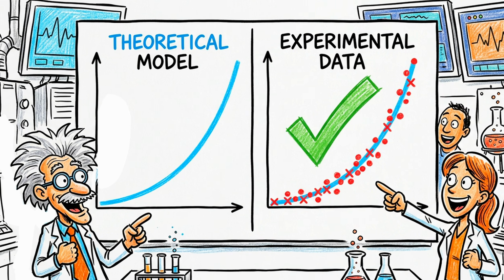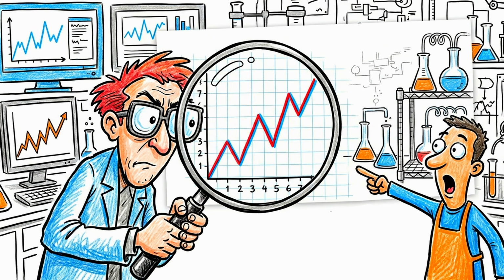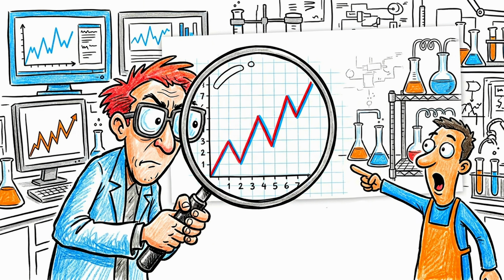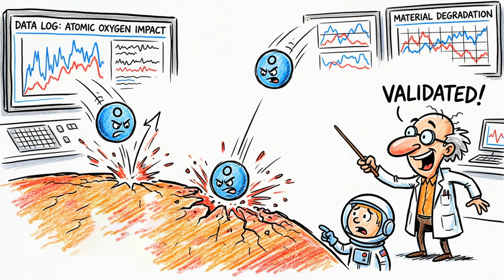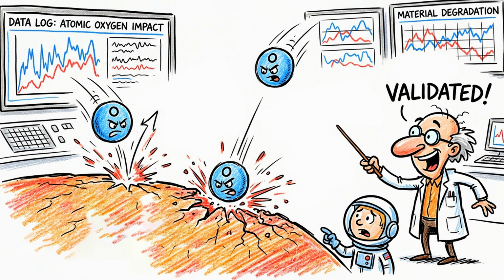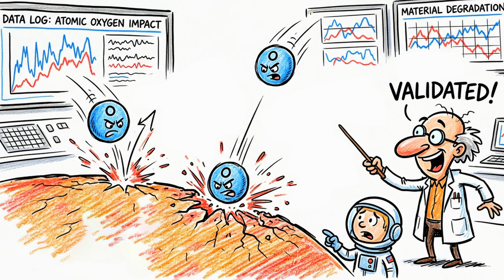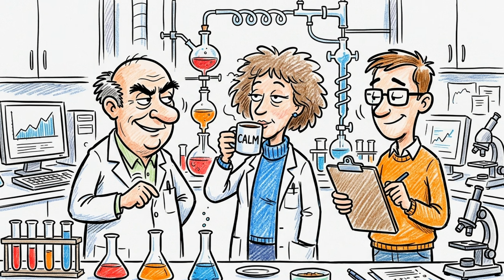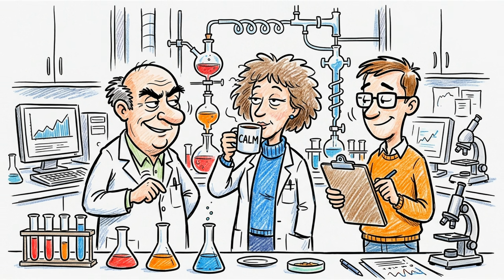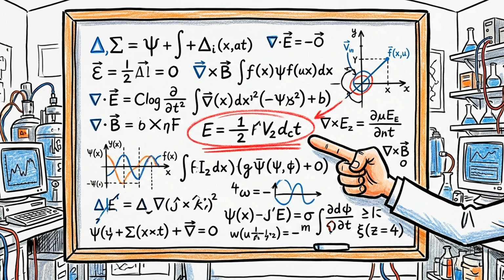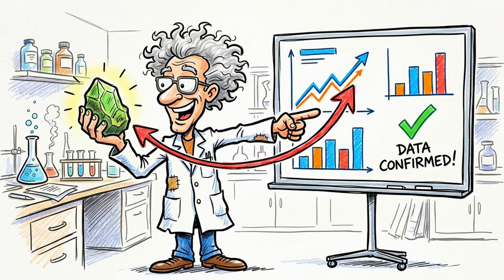Polymer and carbon-based samples showed measurable erosion consistent with the atomic oxygen flux models. The numbers matched. Not in a general way. Specifically, quantitatively, the erosion rates observed on recovered hardware agreed with what the physics of atomic oxygen impact chemistry said they should be. This was not a surprise to the researchers. The physics was already understood. What the measurement provided was verification.